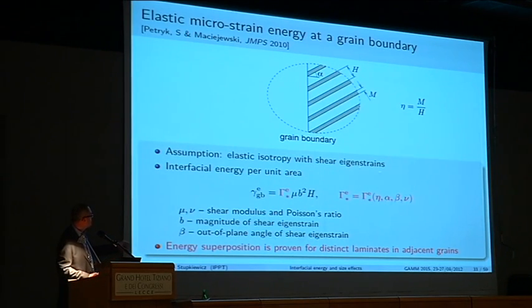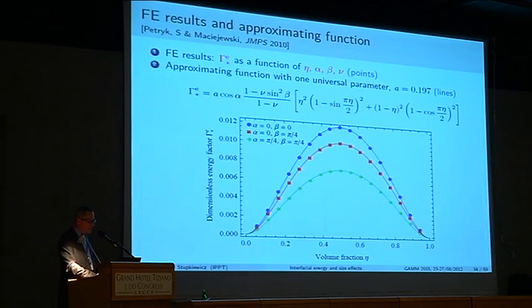So we can introduce this concept of the energy factor. What is important is that we also prove, I don't show you the details, that there is kind of an energy superposition principle, so that you can add the interfacial energy, for instance, if you have on the other side also a laminate in the other grain. So these energies are additive under very weak conditions to be fulfilled. Okay, and that's the result.